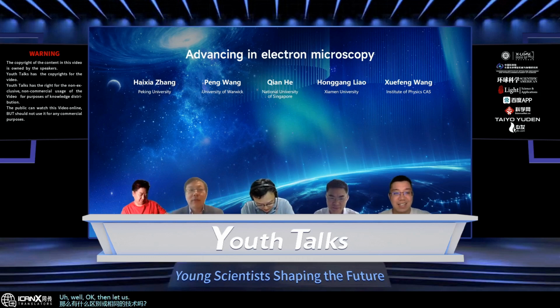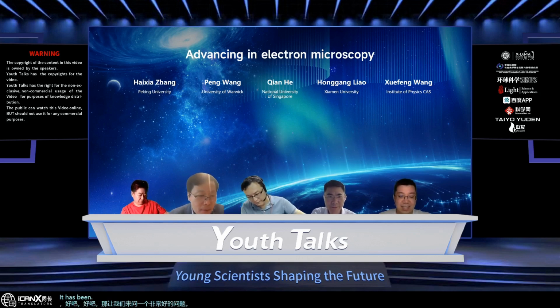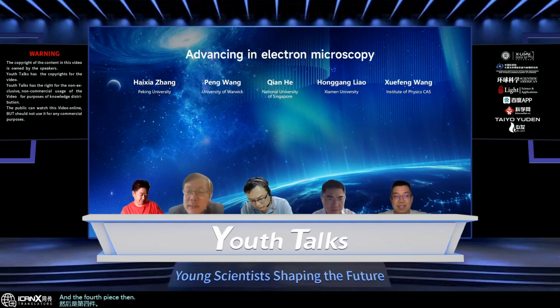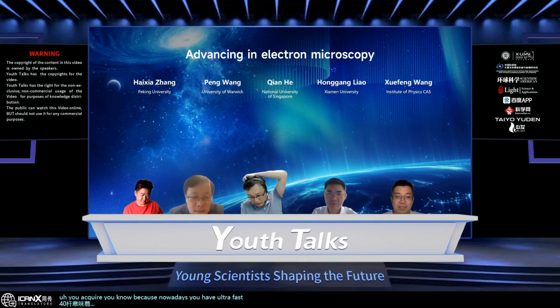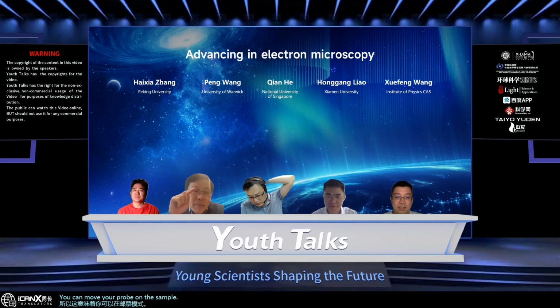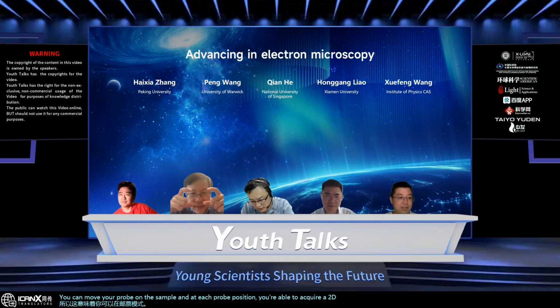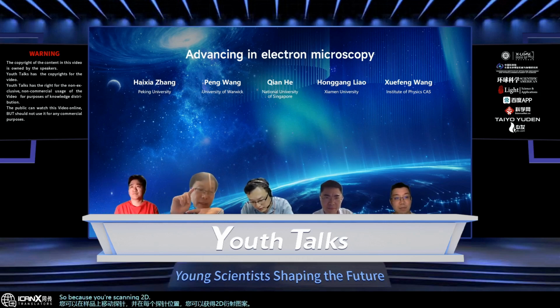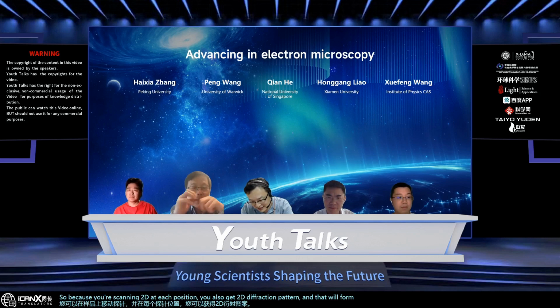Well, that's actually a very good question, and I think this question has been asked quite a lot. The name 4D STEM came after ptychography, and 4D STEM means you acquire, because nowadays you have ultra-fast detectors, which means in STEM mode you can move your probe on the sample, and at each probe position you're able to acquire a 2D diffraction pattern. Because you're scanning in 2D, and at each position you also get a 2D diffraction pattern, that forms a 4D dataset, a 4D STEM dataset.